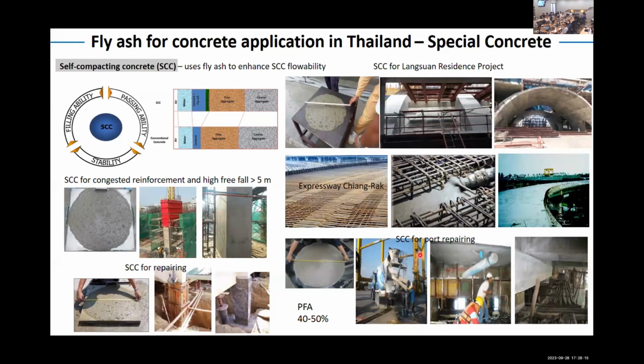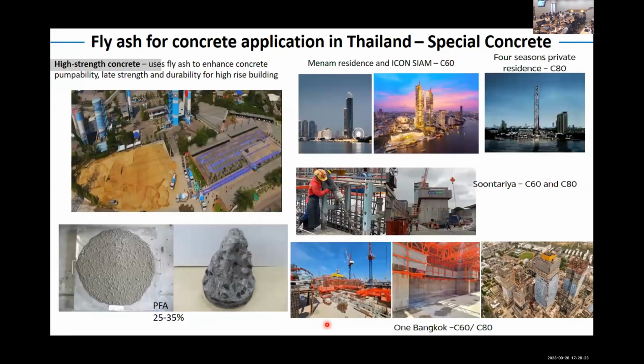Many structures for repairing use fly ash. This one uses around 40 to 50% to repair cementitious. And it is used for high strength as well. I saw it here for vertical members and also horizontal members like a slab.